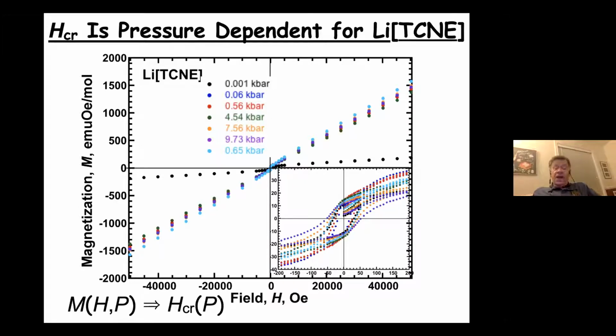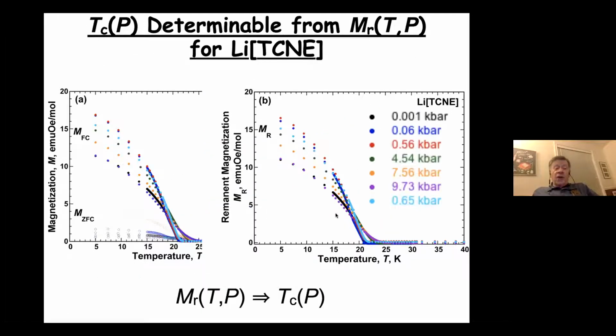So looking at this data, we can see the pressure dependence of the coercivity is evaluated, and I'll show that to you in a couple moments. We can also look at the remnant magnetization as well as the field cooled and zero field cooled, but the remnant magnetization is more important because we can extrapolate the magnetic ordering temperature from it, since we do the remnant magnetization as a function of pressure, we can determine the magnetic ordering temperature as a function of pressure. And I'll share that with you too momentarily.